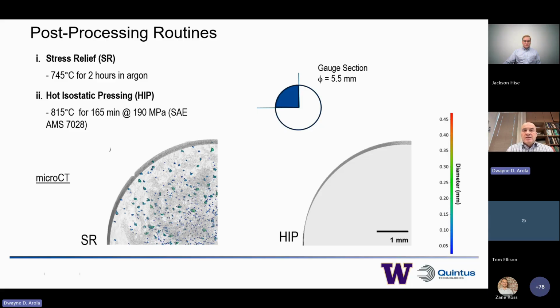high pressure process. And what I'm doing here is showing you an example of a portion of results from micro CT. I'm showing you a quarter section of the gauge section of one of our fatigue specimens. You're looking at the highlighted portion in blue, looking down the axis of the gauge section, comparing the stress relief condition and the HIP treatment. What you're seeing is the distribution of pores within that microstructure. On the left, of course, you see the specks of blue and green. It looks like a large number of them, but that's because we're integrating those pores throughout that particular 30 millimeter length along the gauge section.